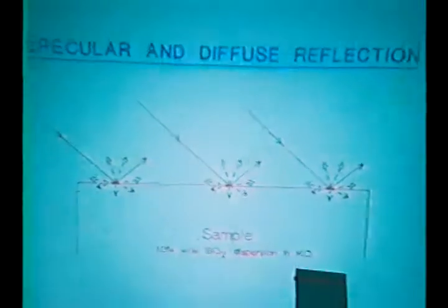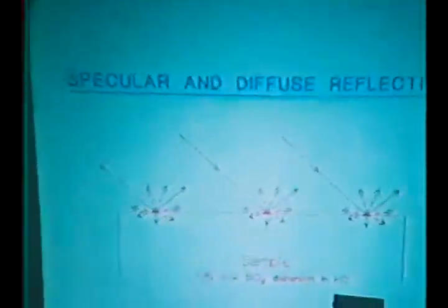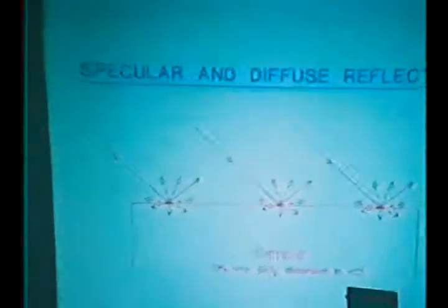Now quickly, here's how the diffuse reflectance technique works. You have a powdered sample. The diffuse reflectance technique allows you to take spectra of powdered samples. We take silica gel or the modified surface or whatever we've done to it and disperse it in potassium chloride at 10% by weight, and place it in a sample cup, with controlled atmosphere and whatnot, because these are very air-sensitive catalysts.